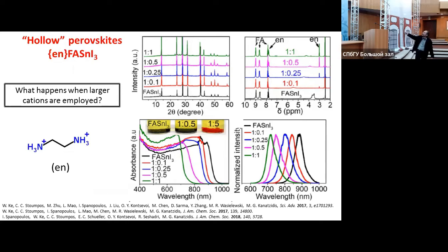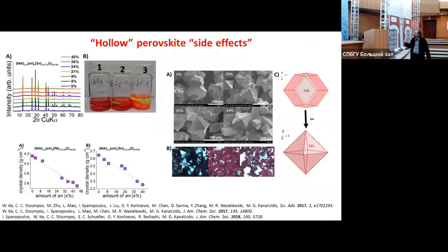And we can also see that ethylene diammonium is incorporated into the structure. We do this by NMR spectroscopy. You also see the bandgap, and it has all the characteristics. What's going on? Other than the optical properties, there are some secondary effects. So for example, you change a typical morphology of the crystals, like this, to this. So basically, you know that somehow it is incorporated.